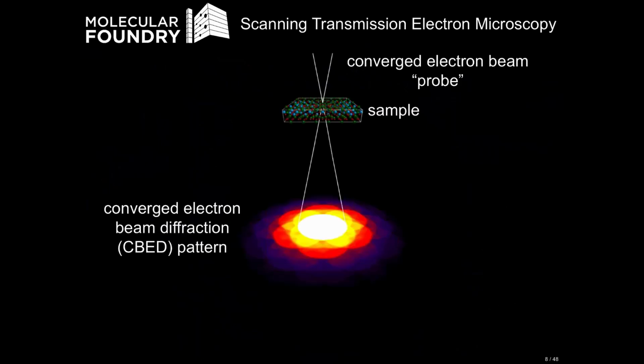And then you place your sample at the crossover point where you have the smallest possible electron probe. For a modern aberration corrected STEM instrument, we can get down to about half an angstrom size of probe, so small enough to probe atomic resolution for most samples. The resulting image that is formed in the far field is called a converged electron beam diffraction pattern, also a CBED pattern for short.